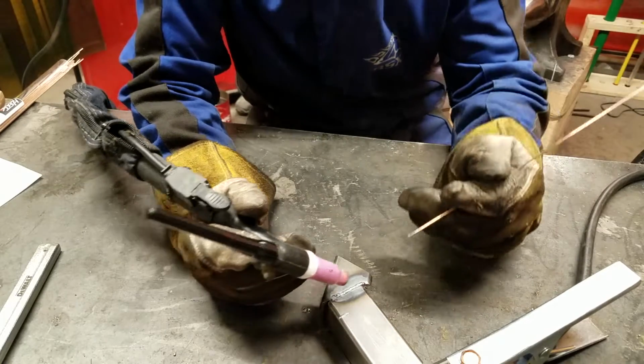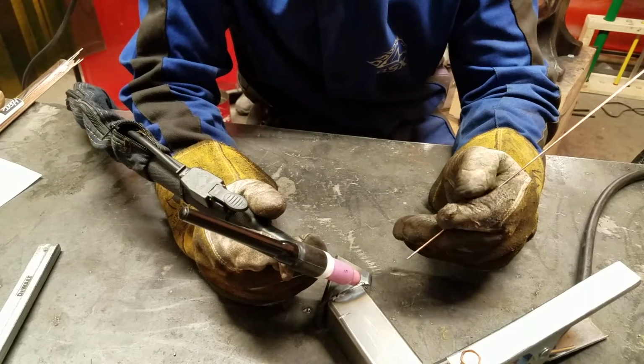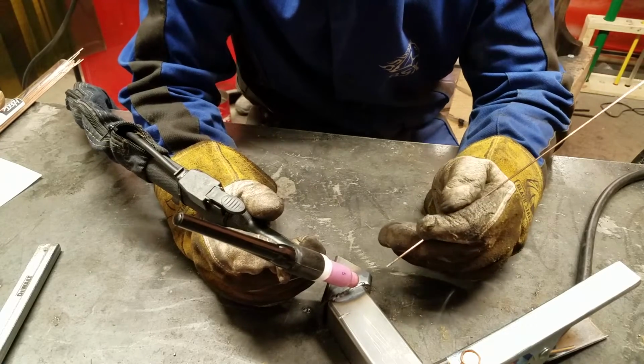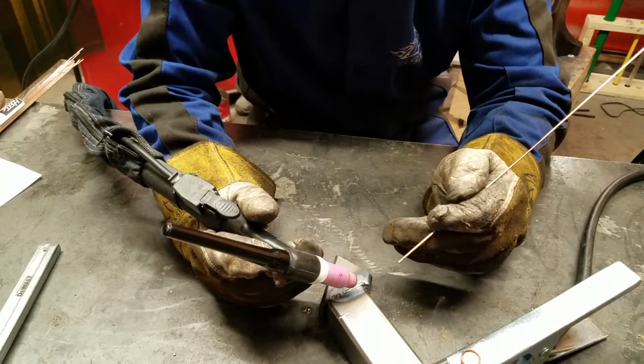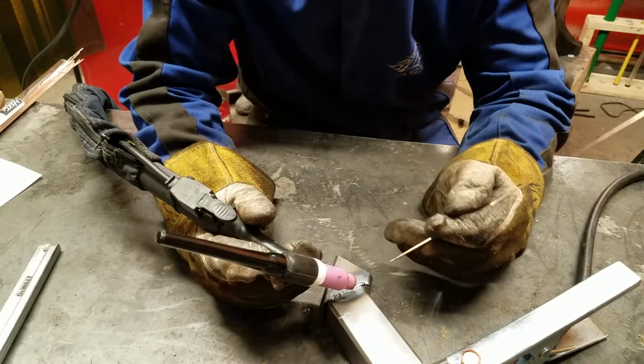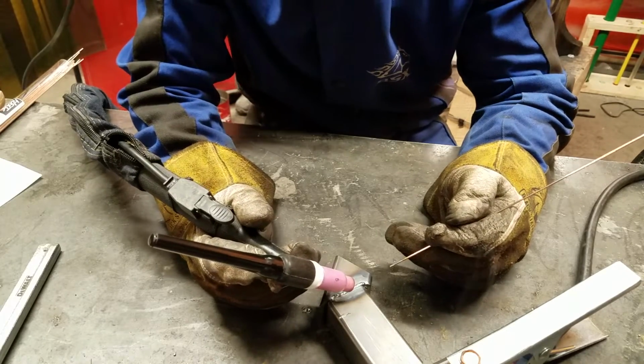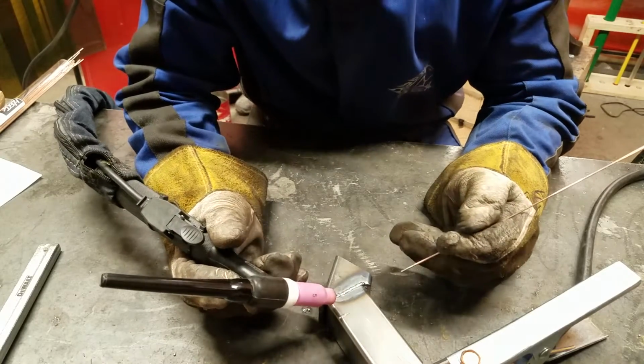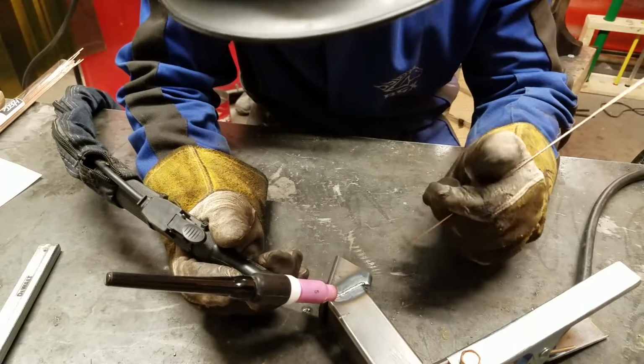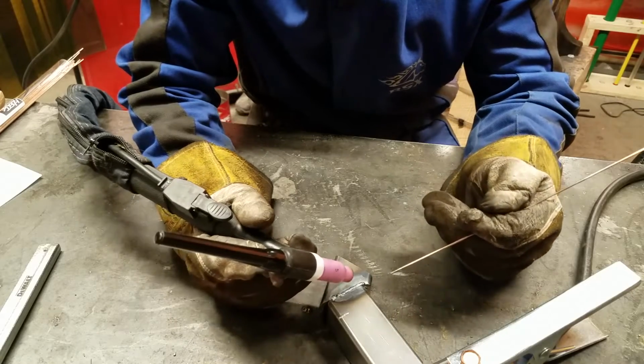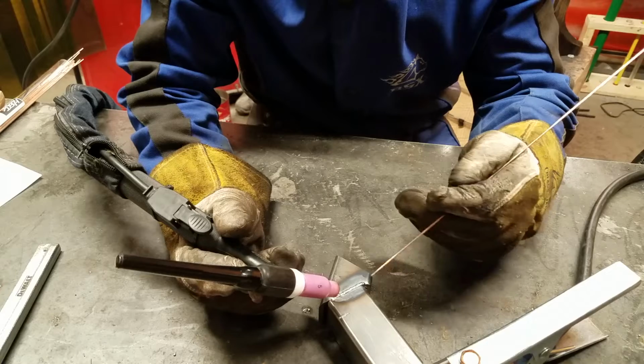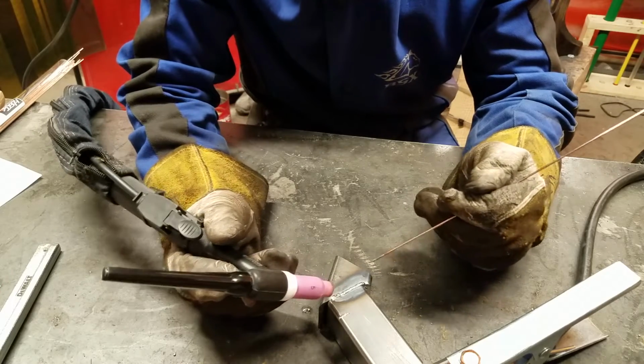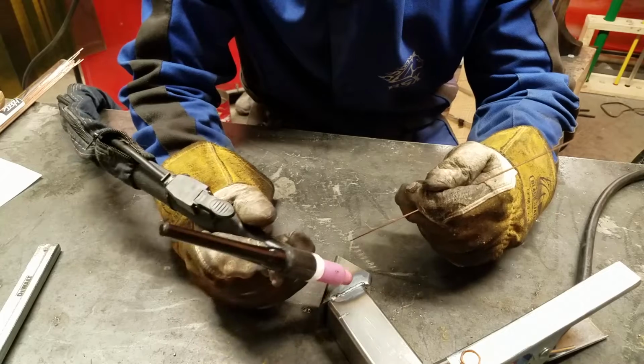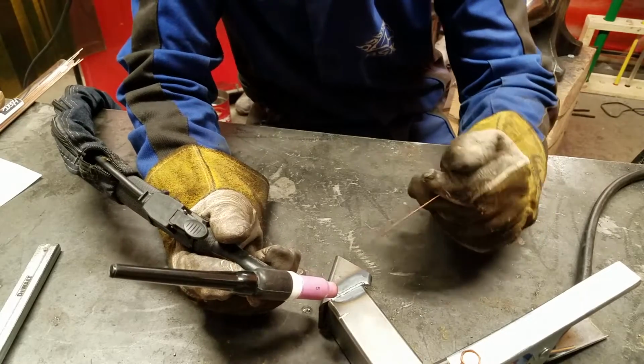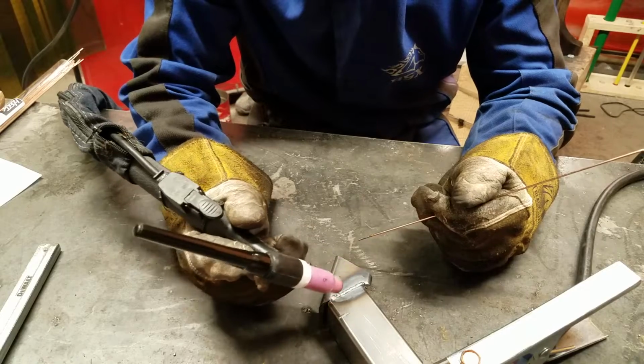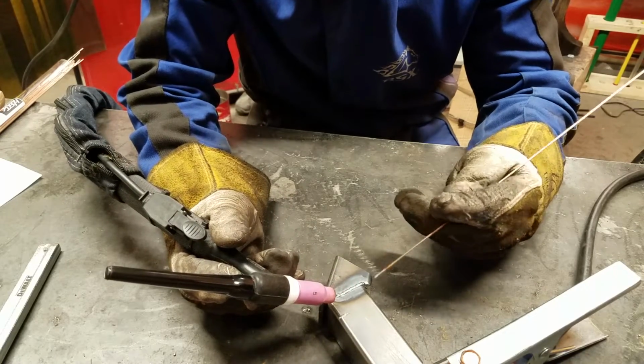So you can see that I stopped when I was still over the molten weld to let it harden up with gas flowing over it. And I can glance over to the flow gauge on the argon tank to make sure that the gas is still in fact flowing. Looking at this weld, it looks okay, but I think I need more power because this weld looks pretty proud. It looks high above the metal versus a little more flush into it. So now what I could do is go back over, we have a little extra metal there, and do a fusion weld where I'm just melting it in to get it a little smoother and get deeper penetration.